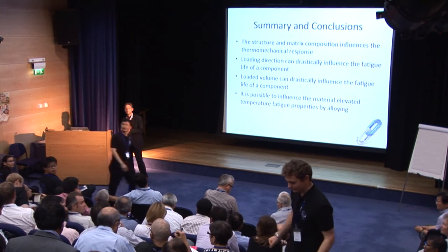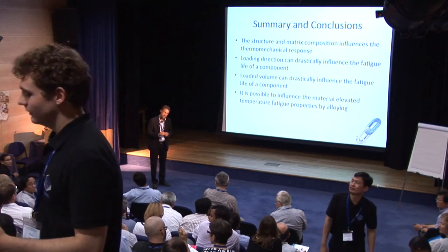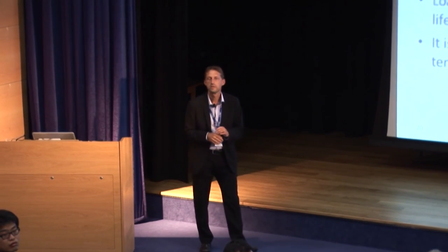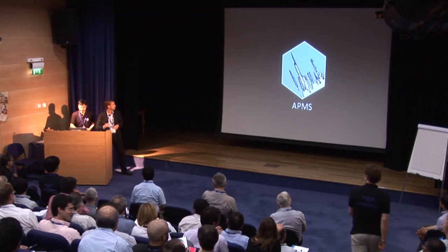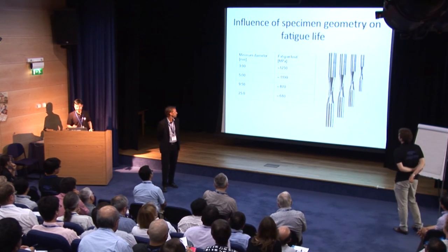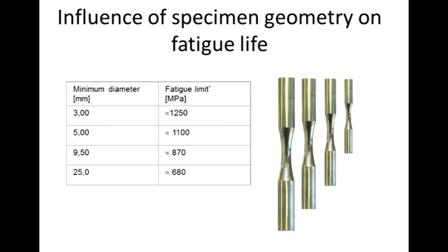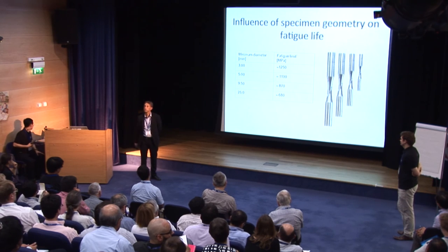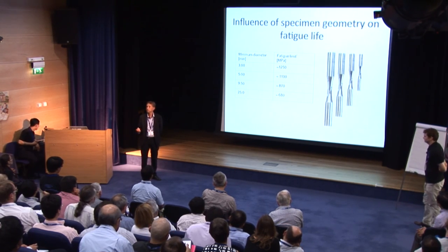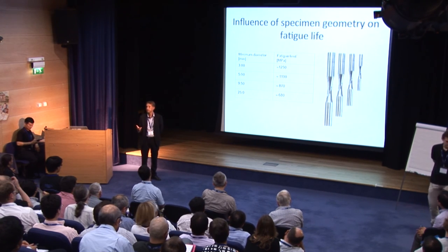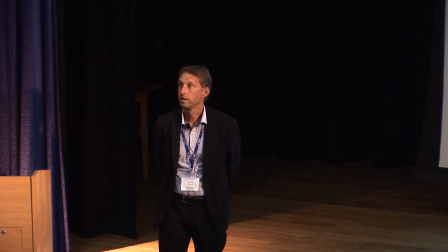Thank you. My question is about your slide on the relationship between fatigue life and the size of the sample. Can you comment on that, and also whether you have checked what particle can actually cause the fatigue, in relationship with oxides, sulfides, carbides? Which slide did you mean? Size of the samples. Yeah, that's the one. We have looked at all the samples that we test, and we ensure that there is an inclusion in it causing the fatigue. If it's not an inclusion causing the fatigue, for example a surface scratch, we have to make a retest, because then we call it a failure. So is this related to the probability of finding a critical inclusion when you increase the size? Purely.